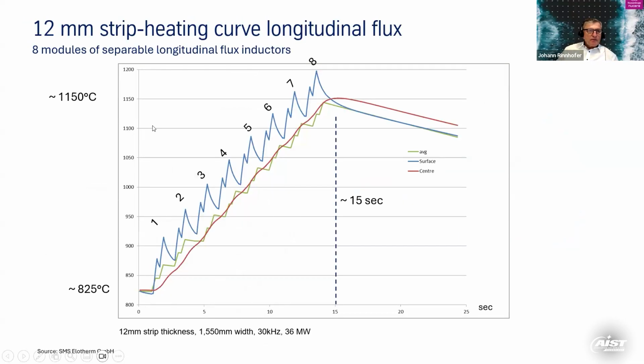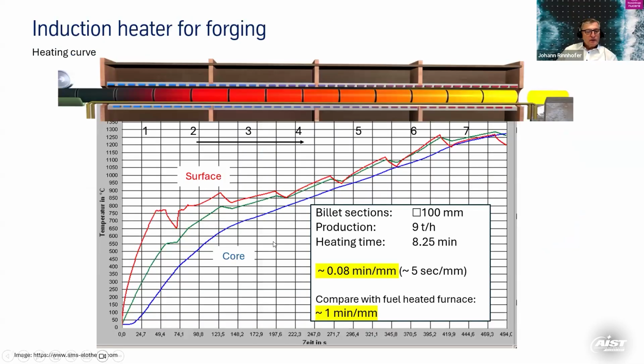You see here strip heating from 800 to 1100 degrees, very quick. In 15 seconds, you can heat a 12 millimeter strip from 800 to 1100 degrees. It's not a lot, no? This is a forge heater. You heat a 100 millimeter square billet in 8 minutes from room temperature to 1200 degrees, ready for forging, in 8 induction coils.